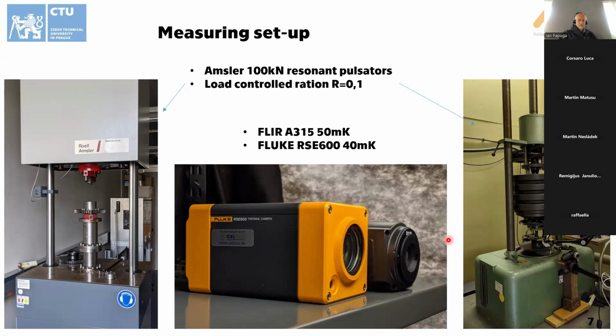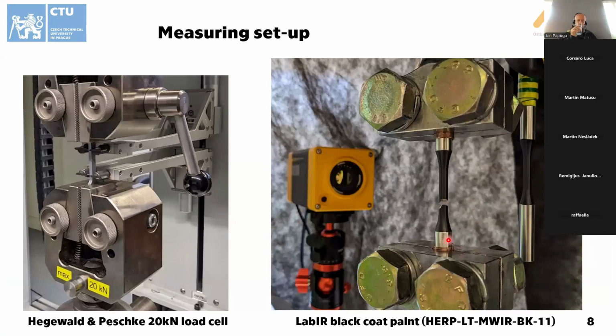For the thermal measurements, we were using Fluke and FLIR thermal cameras, one at Hamburg and one at Prague. On the left side here you can see the tensile equipment. We were using external strain gauges, or external extensometer, and on the right side you can see the setup. Although this picture is for Inconel, it shows well how the setup is, because this is the specimen that is loaded, and this is the specimen that is acting as, let's say, a sensor for the ambient temperature surrounding the testing specimen, as it's better to focus on temperature differences than to use the actual temperature from the thermal camera without reference.